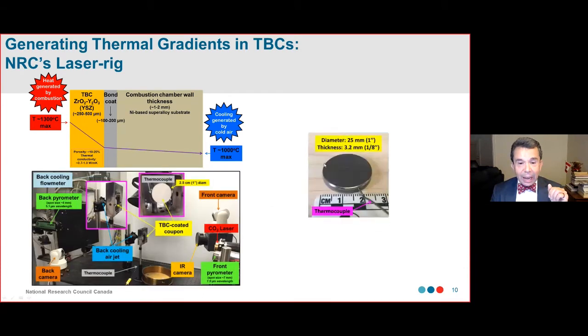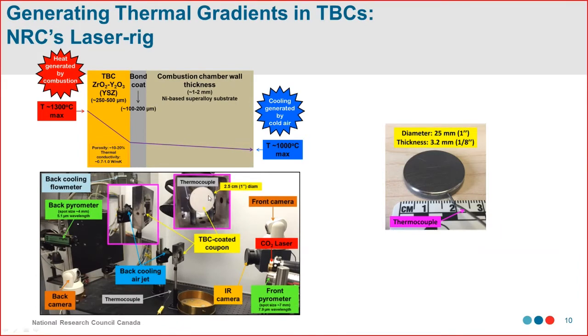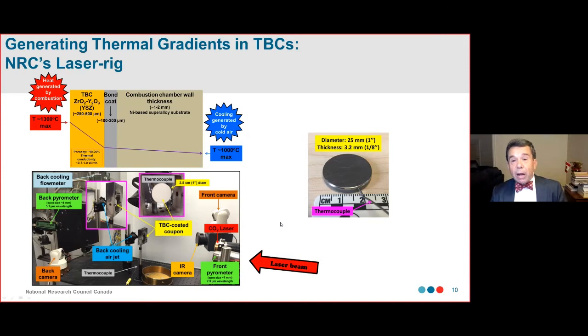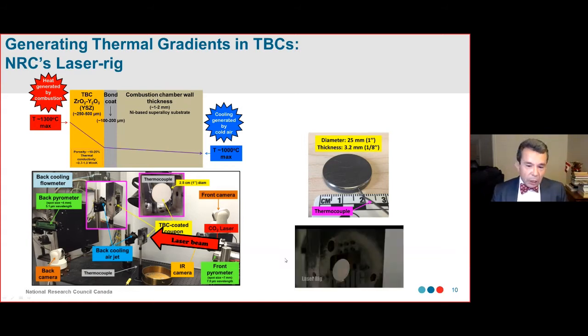Basically, you have a puck-shaped substrate, 25 millimeters in diameter and 3.2 millimeters in thickness, and we insert a thermocouple inside the substrate, and here you coat the TBC. You put it in the rig, and in the rig we have an infrared laser that shines on the sample and heats it up. You can see in this movie the sample coated with TBC, and when you apply the infrared laser, the system will generate high temperature and simulate this part here with thermal gradient.